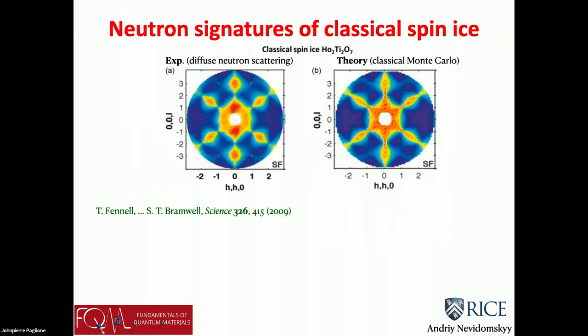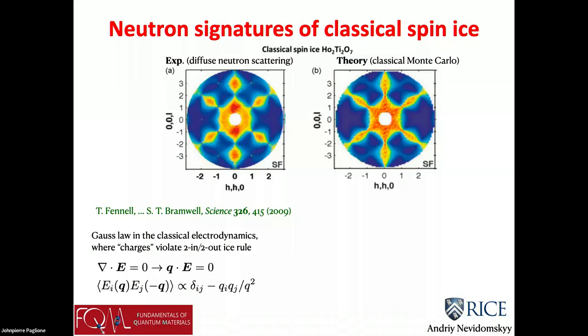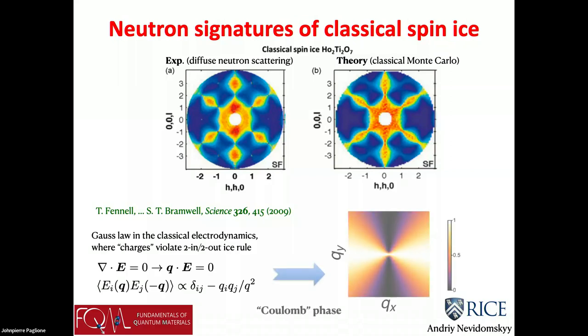Now, if you're trying to do neutron scattering on this compound, the way the spin ice manifests itself, it turns out that there's a very cool analogy to classical electrodynamics. And what you could show is that if you compute the so-called spin structure factor, it's the same as computing the correlator of the two electric field configurations. And in Q space, upon Fourier transforming, it has this particular pattern, which has become known as pinch points.